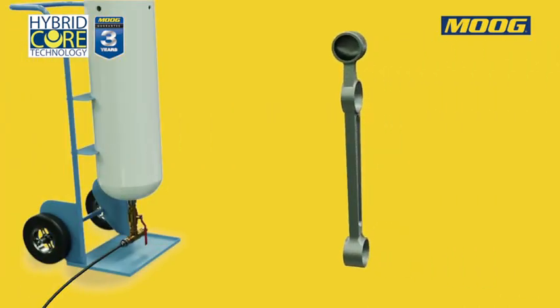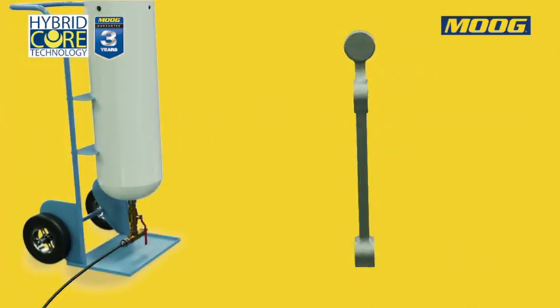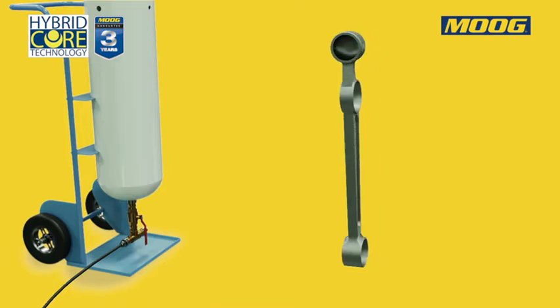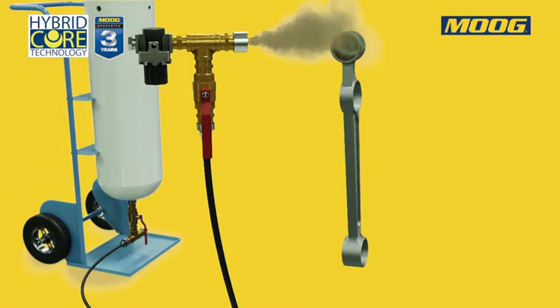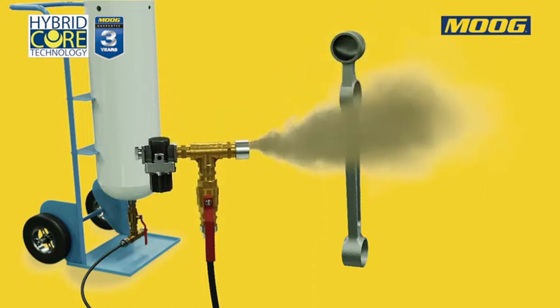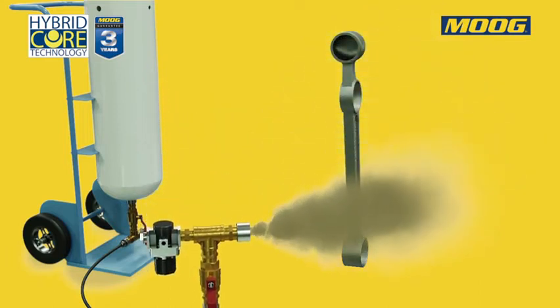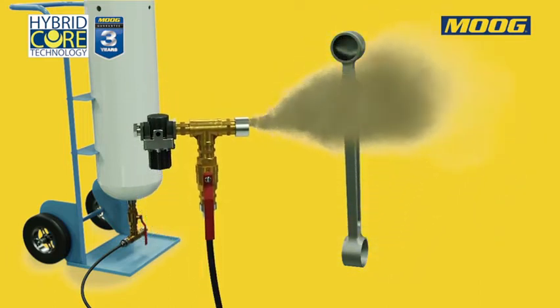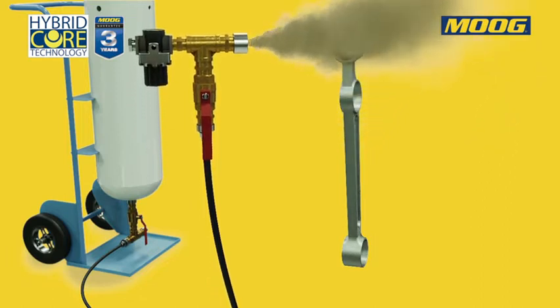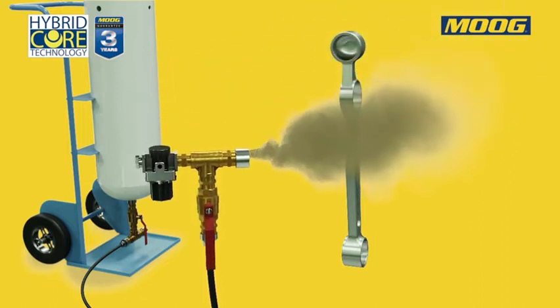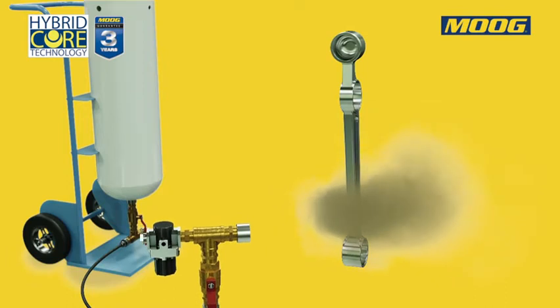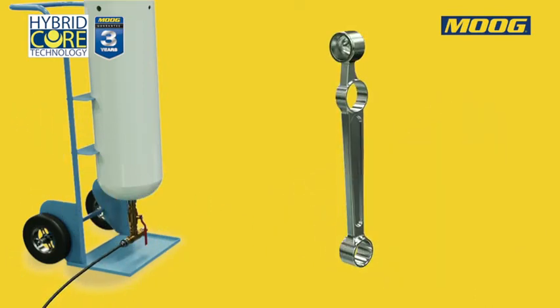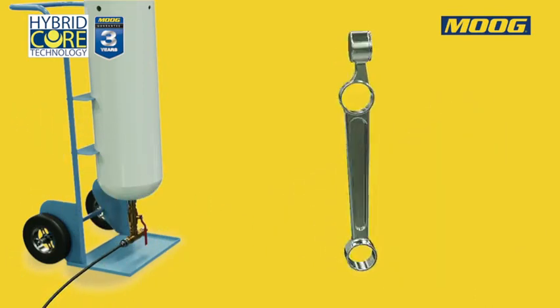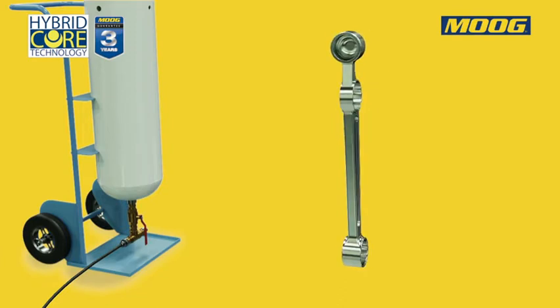To protect the track control arms from this undesirable problem, MOOG implemented sandblasting for the external surface of the aluminium parts. In this treatment, sand is projected at high pressure and speed against the surface of the part to release all those irregularities and local stresses. In this way, a smoother part not only lasts longer, but also has a stronger structure and better appearance.